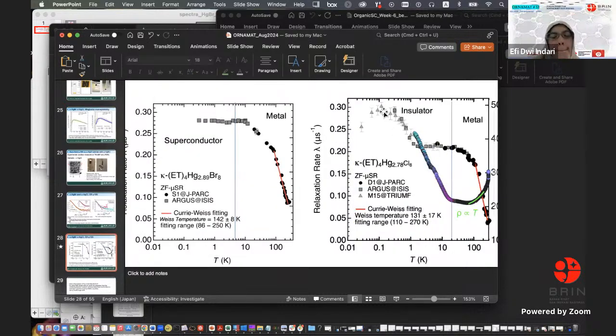So there is a broad peak, even at very low temperature, 0.1 Kelvin. The increasing of relaxation rate around 1 Kelvin indicates that we may have some slowing down of the random spin to be ordered in some way. But then it's very broad. We found that it's decreasing. So maybe this is freezing. Yeah, the spin starts to freeze in the random situation.